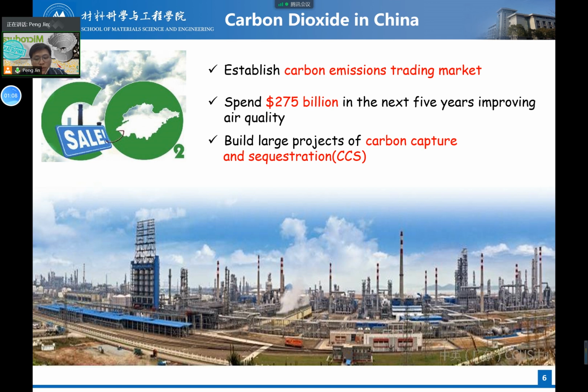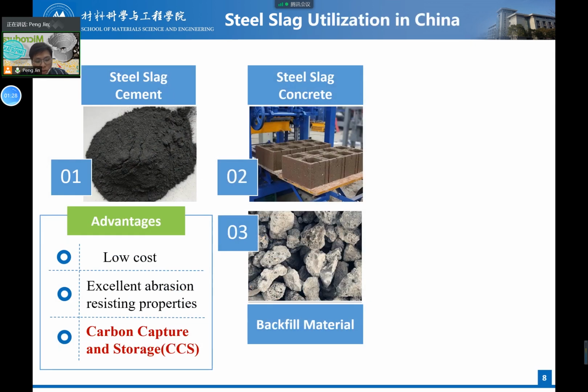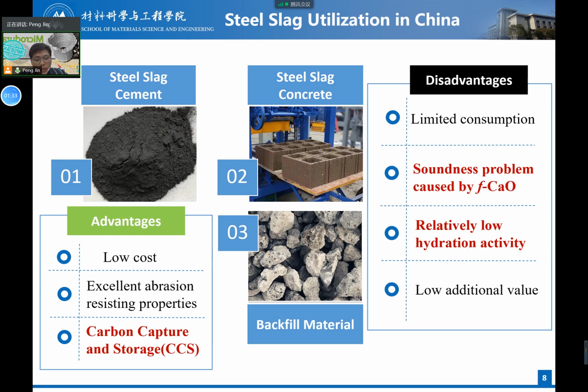As one of the main byproducts of the steelmaking process, it's a huge waste that the utilization ratio of steel slag is still no more than 30%. Steel slag has some similarities with Portland cement, especially the basic oxygen furnace slag. Relatively higher content of C2S induces steel slag higher carbonation activity and makes it possible for steel slag products to be strengthened by means of carbonation.